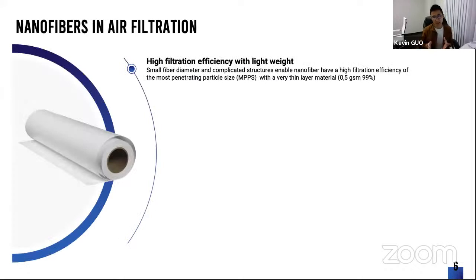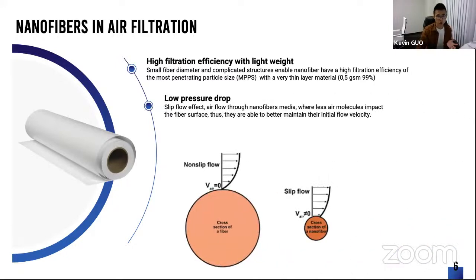In the filtration space, due to the nature of nanofiber filter media, nanofibers with fine fiber diameters are able to construct a complex pore structure, which enables high filtration efficiency for fine particles at the most penetrating particle size. At the same time, to reach the same level of filtration efficiency, nanofiber filter media require much less thickness compared with other regular filter media materials such as melt blown. Nanofiber filter media are also able to offer an extremely low pressure drop due to the slip flow effect.